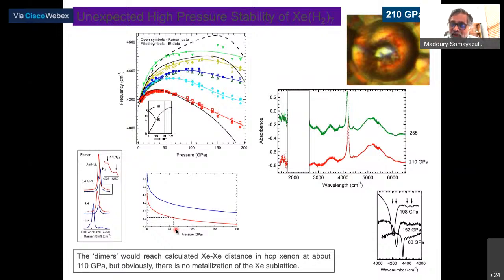Now, that is a big surprise to us, but in terms of the sodium result which I put up earlier, it tells you that life is not so simple. So in other words, you can have a material like xenon, which is highly electron donating in the hydrogen sublattice, and it will do nothing to the hydrogen metallization or change the pressure of hydrogen metallization. Obviously, because what is happening is as you increase the pressure, the electron density seems to be spilling into the interstitial regions. So I think in a way it was linked to that.